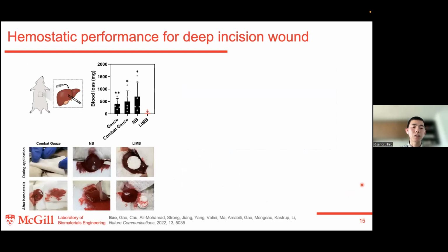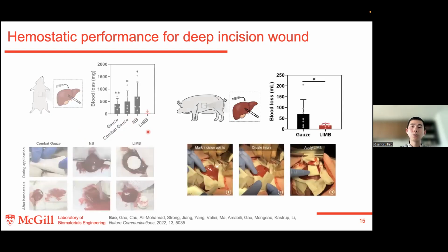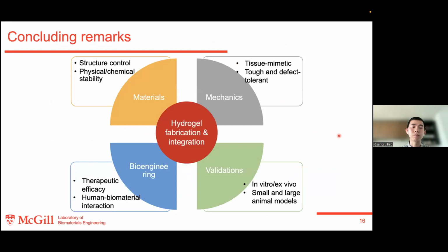The adhesive is also effective in stopping deep incision wounds. For example, it reduces the blood loss significantly compared to the standard gauze treatment, the commercially available combat gauze, which is used in the military, and also the non-structured bioadhesive counterpart. And also in the large animal models, it reduced the blood loss compared to the standard gauze treatment by more than 35%. So it is very effective in both small and large animal bleeding models.